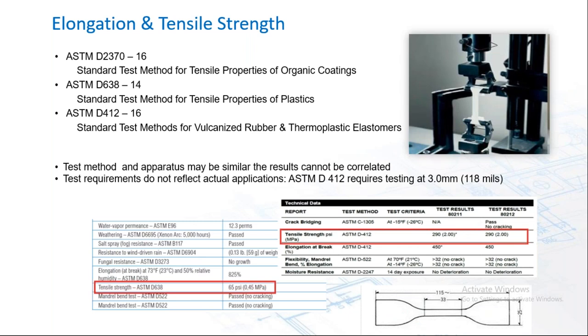Elongation and tensile strength, there are three different tests for this, and sadly, not many of these ASTMs were developed with the coatings industry in mind, so we've had to adopt, modify, and apply as we see fit. The test method and the apparatus are similar, but the results of these three tests really can't be correlated.